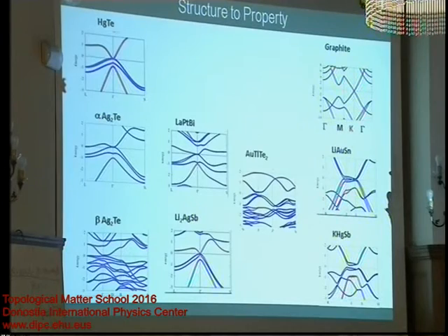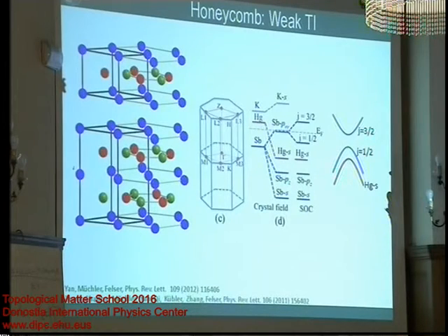It's hexagonal. But he did some calculation and came back. He said, okay, yeah, the s electrons, everything fits. It's really nicely inverting. And the compounds exist in two different structures. One is like the honeycomb, with a smaller unit cell, and one with a bigger unit cell, because the mercury antimony is sometimes like that, the mercury is sitting over an antimony. So you need two layers and it has a bigger unit cell. But it doesn't make a small difference in the properties, which is surprising.